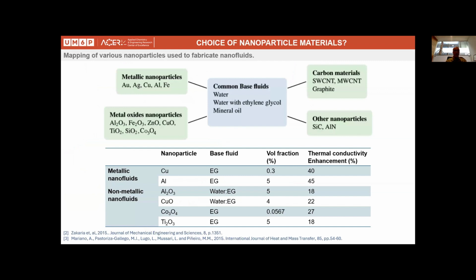So speaking about materials, of course, we have choices. Either you use metallic nanoparticles injected in conventional heat transfer fluid or base fluid like water, oil, or mineral oils in general. One can think about carbon-based materials such as single-walled carbon nanotube, multi-walled, or graphite. If I'm looking at the literature, these materials contribute hugely due to their 2D dimension structure. They create a network within the fluid and contribute hugely to enhancing thermal properties. Unfortunately, these materials are expensive to produce. So that is the issue.